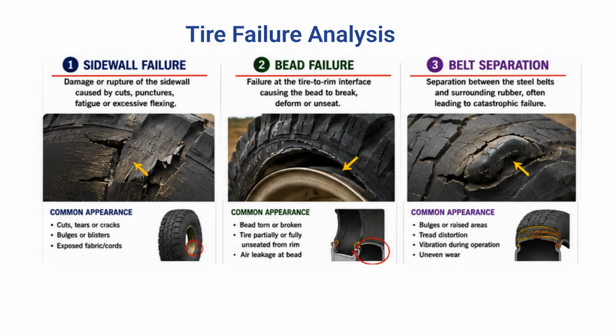The third is belt separation, where the internal steel belts separate from the surrounding rubber. This may produce bulges, distorted tread, vibration, and uneven wear, and can lead to sudden, catastrophic failure. Overheating, high-speed operation under heavy load, impact damage, and manufacturing defects are common root causes. Recognizing these symptoms early helps engineers identify the failure mechanism, correct the operating condition, and prevent repeated mission failures.